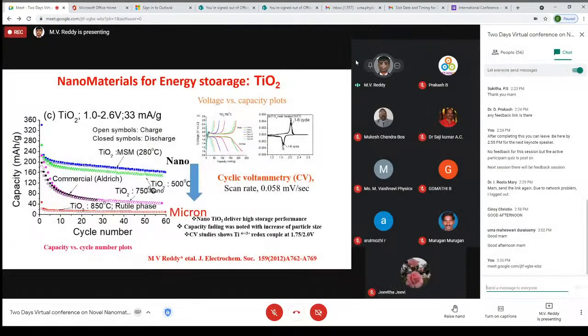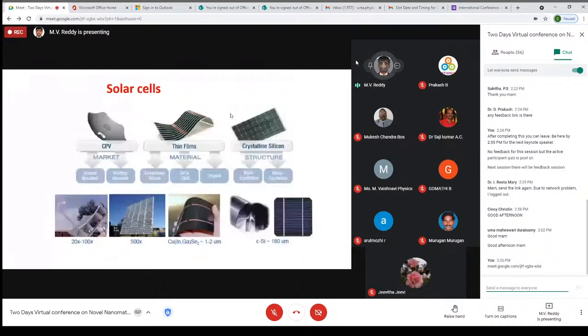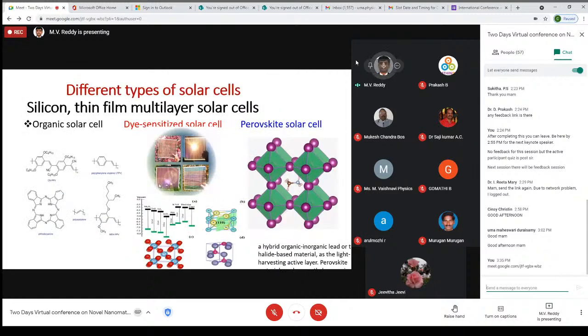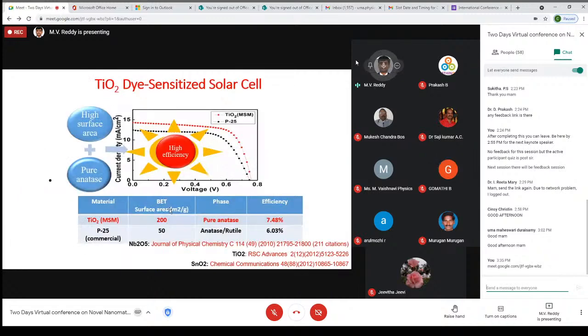If you go from nano size to micron size, for energy storage nano seems to be better compared to micron size. Solar cells are one of the important things, since thin film solar technology has already been demonstrated. As academic researchers, people are concentrating on different types of organic, dye-sensitized, and recently perovskite type solar cells. One example, the dye-sensitized solar cell: we can get slightly improved performance, like 7.48, by using our high surface area material.